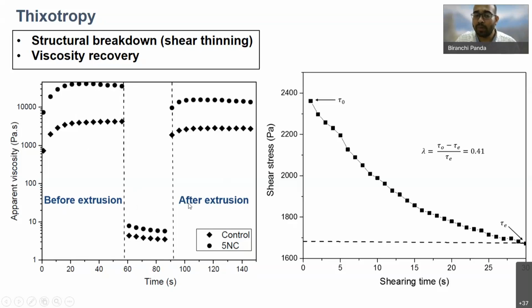But after you deposit this material on the print bed, it should have the capability to recover its original viscosity, or else it is simply going to spread away on the bed. You can see the material that we printed has the ability to recover almost 80 to 90% of its original viscosity, which is really good, because this higher viscosity on the print bed helps maintain the shape of the filament according to the nozzle shape. So this is how we always characterize new materials to fine-tune the mix for concrete printing application.